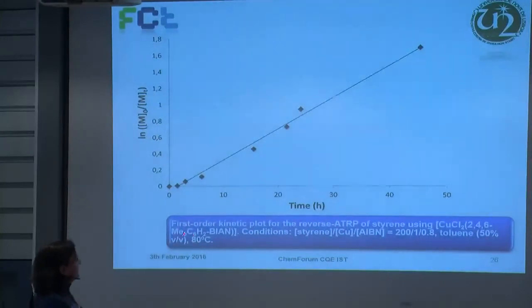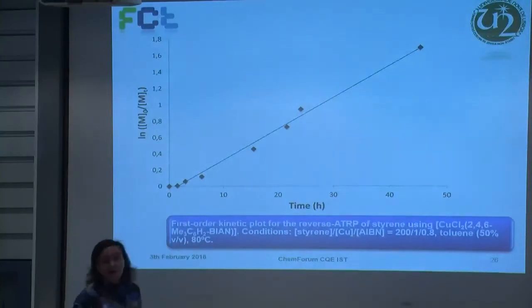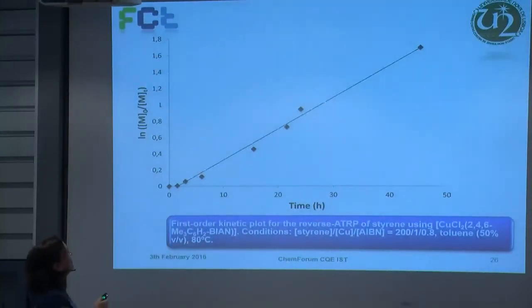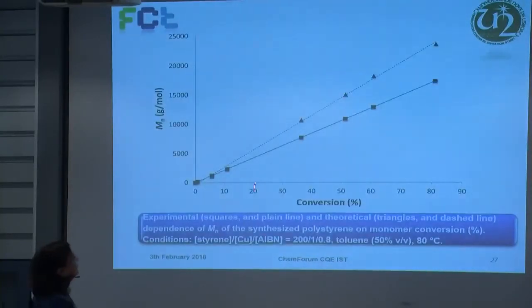And the conditions were styrene, copper, AIBN, 200:1:0.8, in toluene, 50% volume, at 80 degrees centigrade. So in this reaction, this compound acts as catalyst, and the conversion is also represented here. And we compare the experimental, squares and plain line, and theoretical, triangles and dashed line, dependence of Mn of the synthesized polystyrene on monomer conversion.